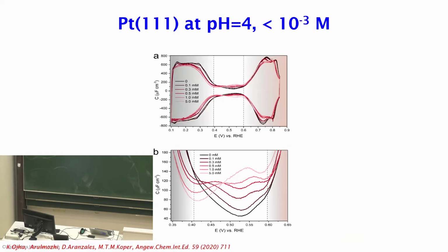So we expect that this minimum should be at 0.53, 0.54. That's not too bad. But more importantly, as we add electrolyte without changing the pH, the minimum stays where it is. The capacity just goes up, just as in the experiments of David Graham. And so we thought, okay, this is it. This is the potential zero charge, but at anomalously low electrolyte concentrations. We shouldn't see this at these low electrolyte. We should see it already at 1 millimolar, and we saw it at much lower concentrations.